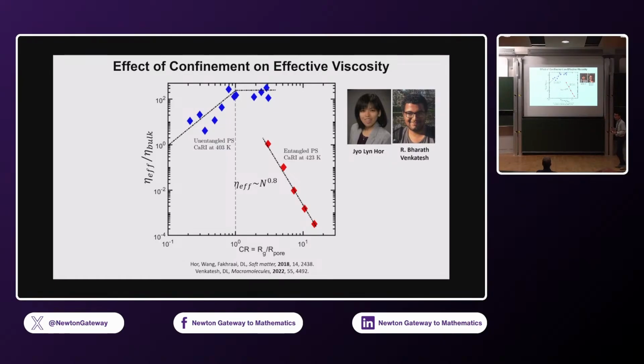When we have very short polystyrene that is unentangled in its melt state, and we see what happens to this normalized viscosity, you see that it actually goes up, and then plateaus at some value when it hits a confinement ratio of 1. Okay? Now, interestingly, when we go to very, very large polymers that are very highly entangled in their melt state and do the exact same experiment, what we see is that this effective viscosity, when compared to the bulk viscosity, is much, much smaller. It's as small as 3 or 4 orders of magnitude. So polymers are able to move much faster than what you'd expect from the bulk state.